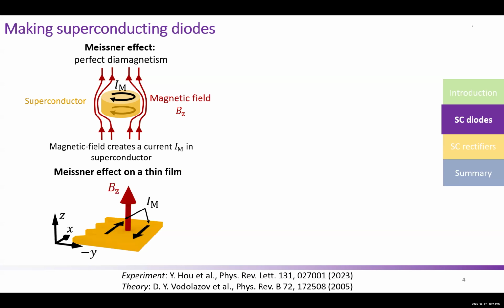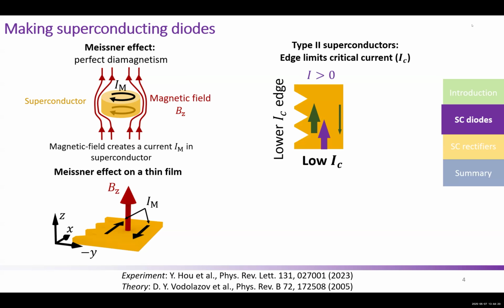Now, if we make a device which is just an ultra-thin stripe of a superconductor, we apply a magnetic field perpendicular to the plane. That means that at the opposite edges we're going to have opposite Meissner currents, as you can see here. Now, since this is just the top view of the sample, when you apply a positive current, meaning that it's going up, as this purple arrow shows, we have that at this edge we're having a very high current, but at this other edge we're having much smaller current. If we reverse the current direction, then this edge is the one that has more current.